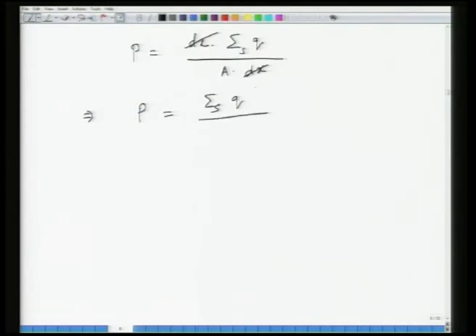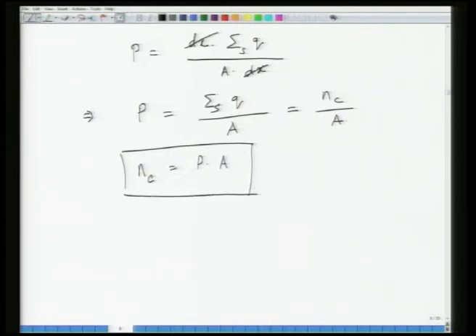So, if this is the polarization P, then P can be written as dx sigma sq divided by A dx. The dx cancel each other. As a result, P becomes equal to sigma sq, which is nothing but the total surface charge, divided by A. So, total surface charge is what? Nc, right, divided by A. So, Nc becomes equal to P times A. So, total surface charge is nothing but polarization multiplied by the surface area.